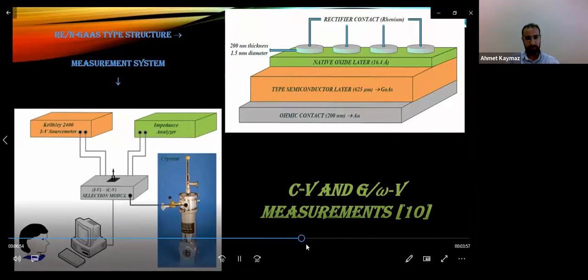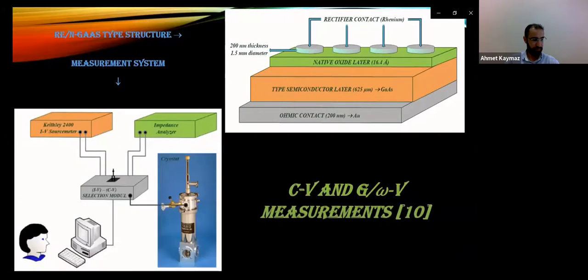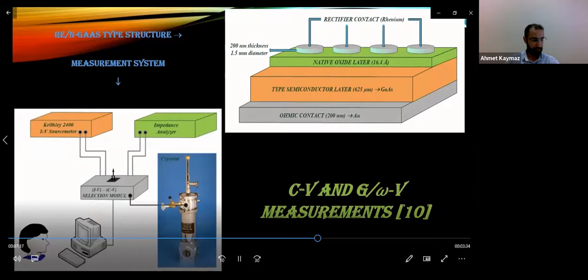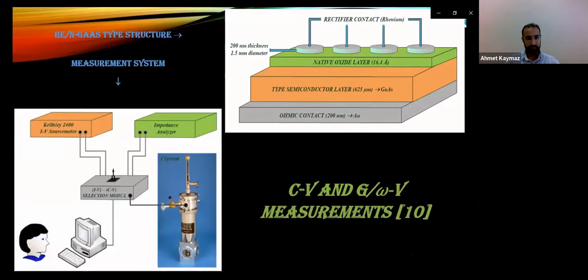However, at high enough frequencies, that is, at frequencies of 500 kHz or greater, these charges cannot follow the AC signal, and so their contribution to the measured capacitance and conductance can be negligibly small. Therefore, the CV measurement was carried out at high frequency for the reliability of the measurement and its results.